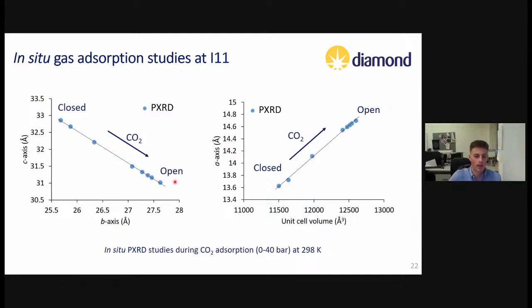If we look at what happens to the framework when we increase pressure, we started off looking at CO2 going from vacuum to 40 bar at 298 Kelvin. What we see is that even under relatively low pressures, you can force that framework to reopen. So you see a gradual expansion of the B-axis, concerted compression of the C-axis, and again that A-axis reopens. So you go through that ligand flip.